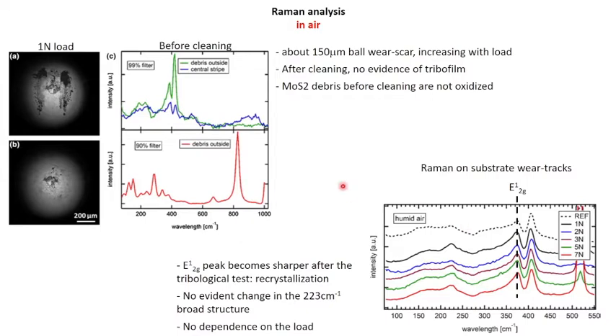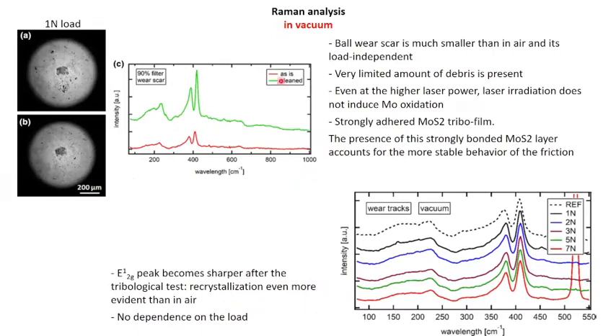Repeating the same analysis in vacuum, we have that even before cleaning the surface here, we do not have any evidence of debris on the surface, but we can observe the presence in the wear scar of this dark area. Doing the Raman analysis on this black part, using the higher power, the one that on the debris generates the oxidation, you can clearly see that here in red we have the presence of the MoS2 film. So we have the generation of a tribofilm composed of molybdenum disulfide, which is probably the reason for the low coefficient of friction experienced in vacuum or in absence of humidity.